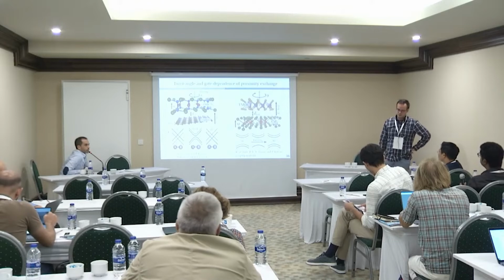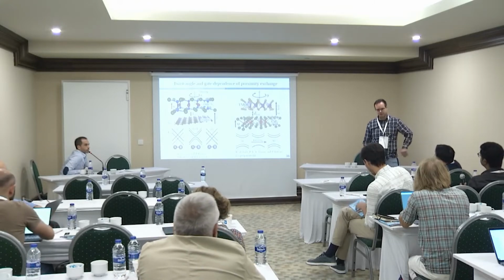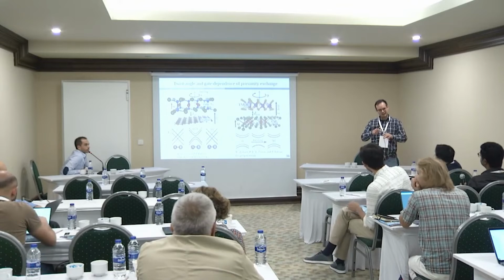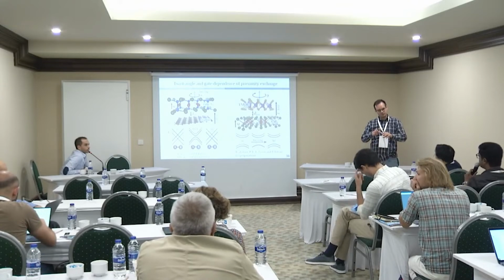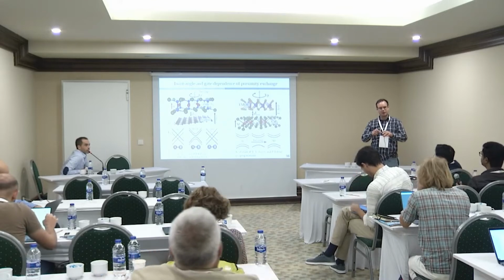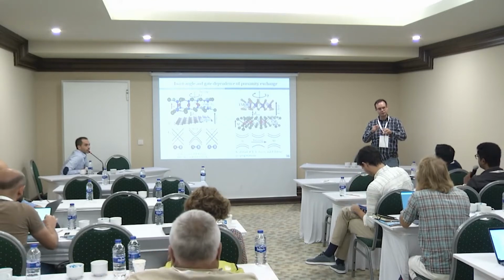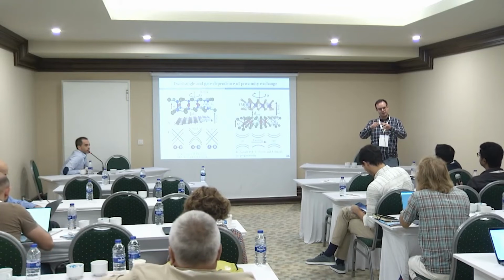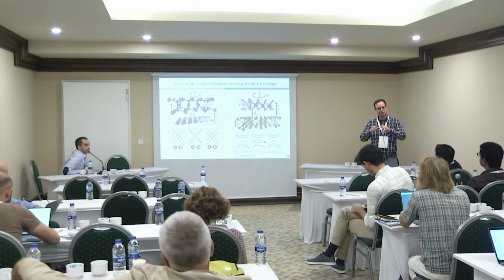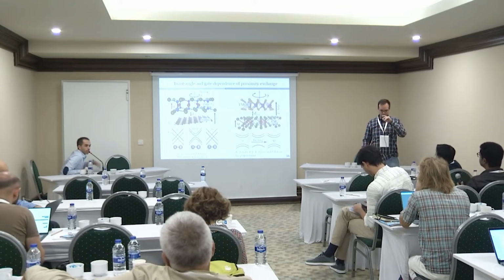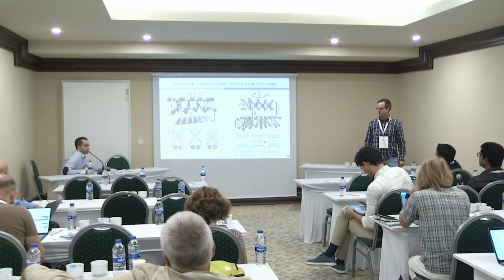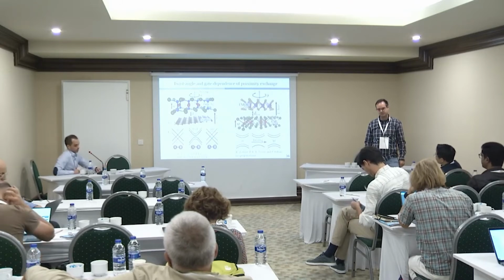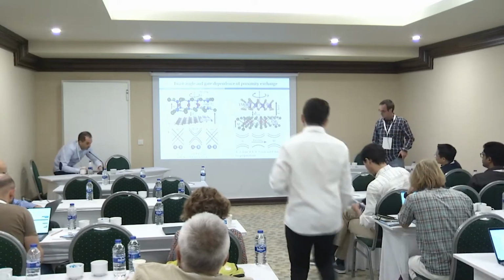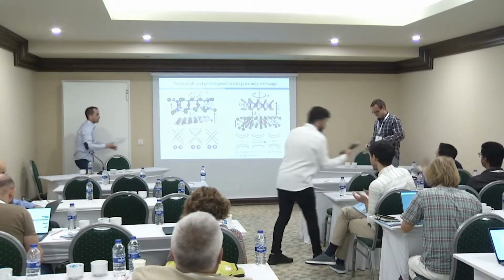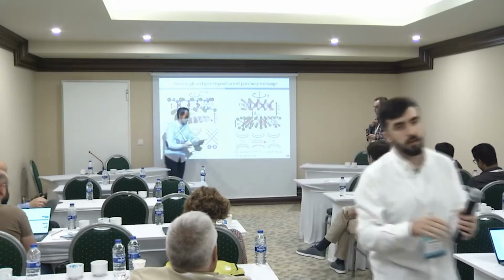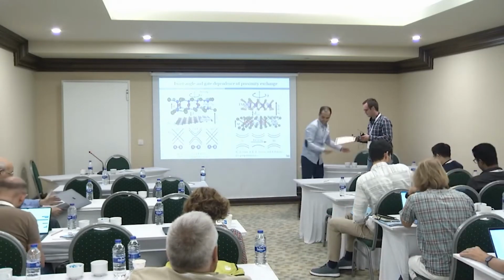Yeah, so I guess what happens once you shift the Dirac cone within the band gap, you can tune the proximity. For monolayer graphene, there is no band gap. No, within the band gap of the TMDC. So you shift your Dirac states within the band gap, and thereby you affect the proximity spin orbit coupling. How it will depend, we can discuss. Okay, sure. Yeah. So thanks again for the talk. Yeah, thank you.